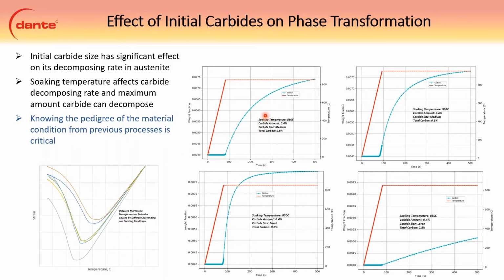So the top left and bottom two all show 850 with a medium size carbide, small carbide, and large carbide. And this is the carbon going into austenite. You can see that the small carbide dissolves really quickly, whereas the large carbide dissolves very slowly and doesn't even fully dissolve in this time. And then this is the medium carbide size figure on the top right at 950 instead of 850. So you can see it goes a little bit quicker at higher temperature dissolving.